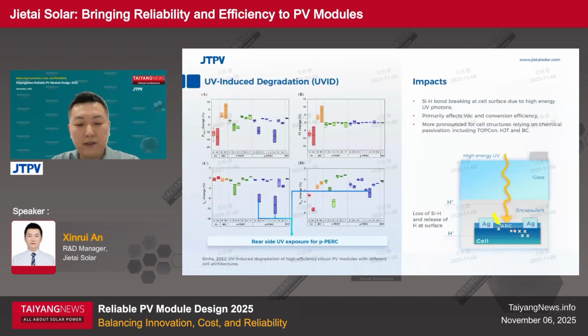Since 2023, UV-induced degradation has been a very hot topic within the PV community. Although the detailed mechanism of UVID is still not that clear, it is generally believed that the high energy of UV photons can break the silicon-hydrogen bonds at the front surface of the solar cell. And this is supported by the fact that such degradation primarily affects the open circuit voltage of a solar cell.